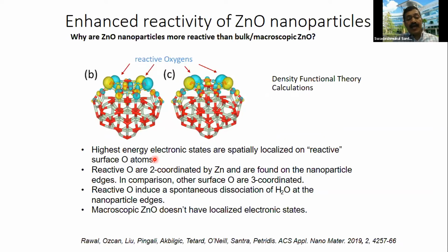Well, as you make smaller and smaller size particles, you create more surface defects. In quantum dot nanotechnology, for bioimaging and drug delivery and so on applications, you try to passivate the surface to make it perfect so that the optical and optoelectronic properties are retained. In this application, you don't want that. You want just the opposite. You want to create defects.